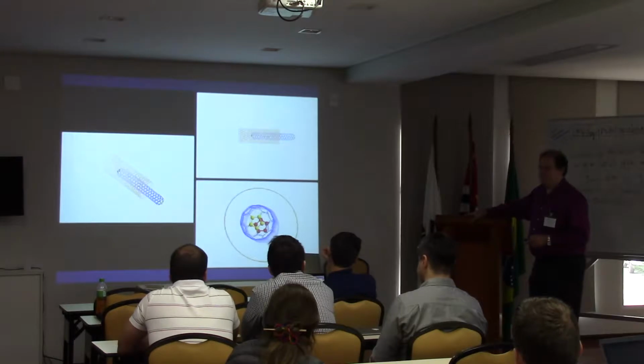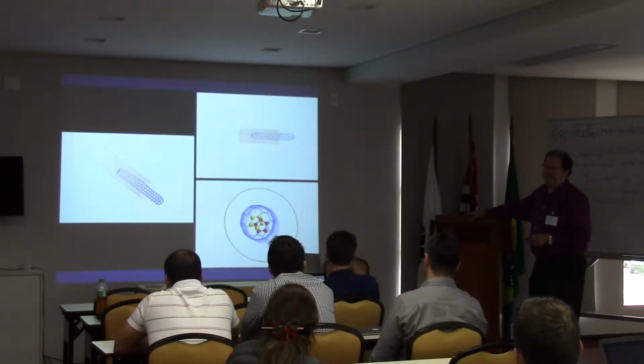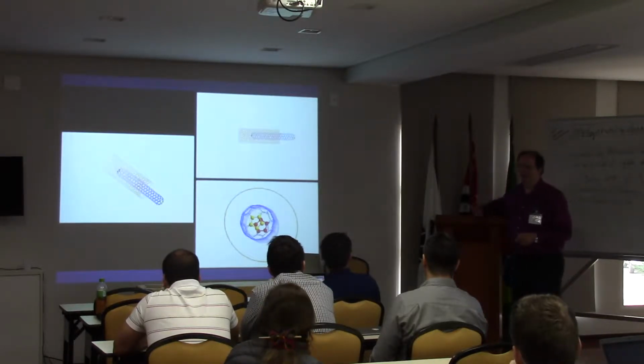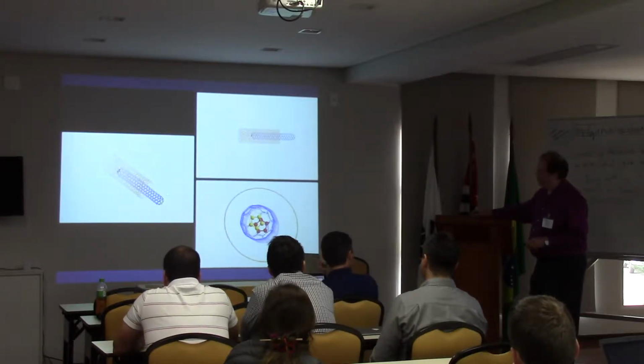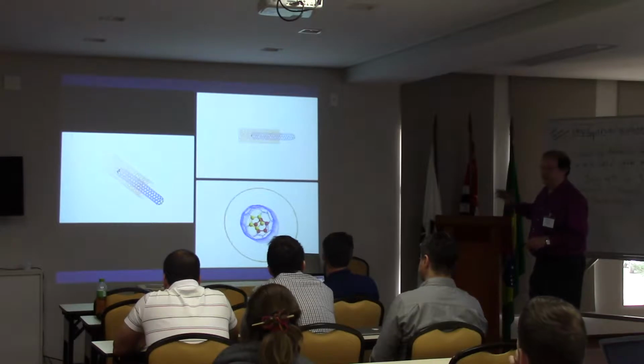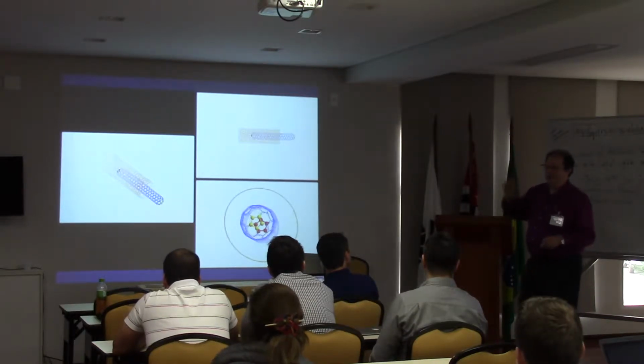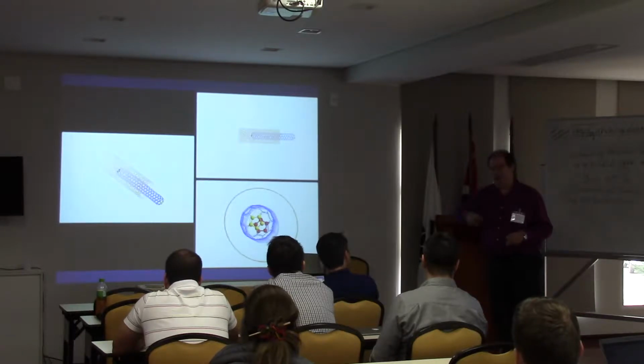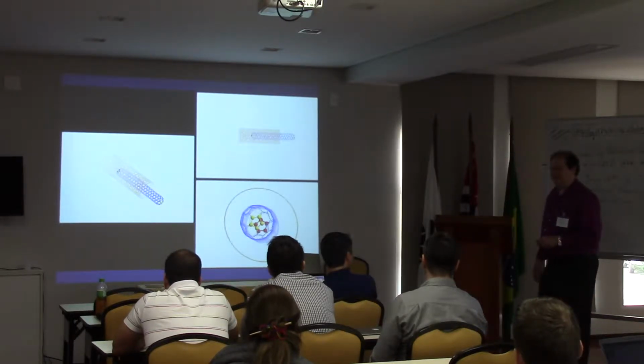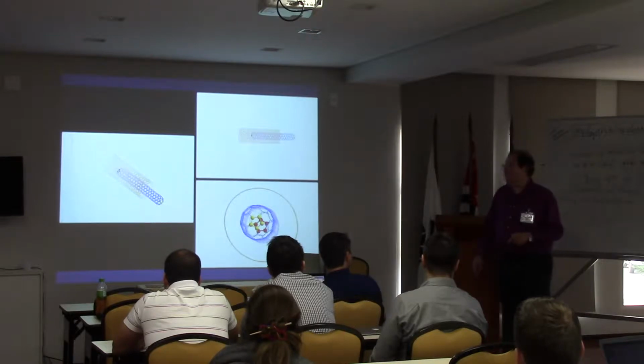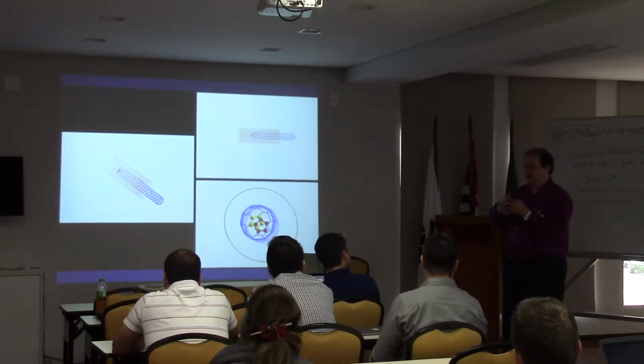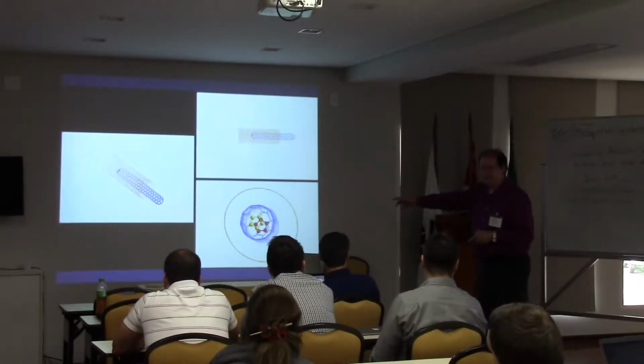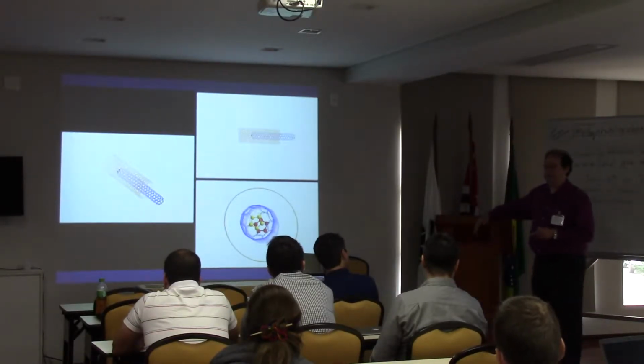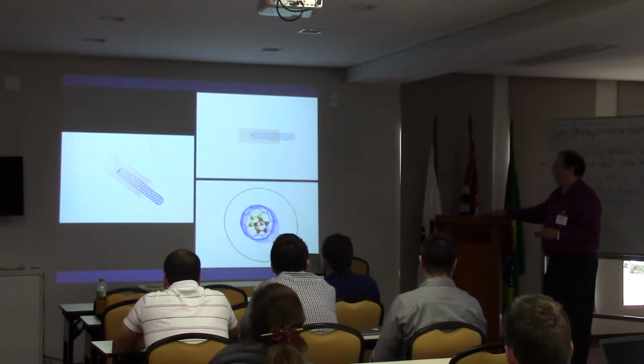So in this simulation, you have actually pulled the inner one back? No, we just gave it an initial velocity, a kick, and then it keeps going back and forth. When it's close to the end, the van der Waals interaction pulls it back. When it's inside, it's the opposite. So it's like a real pendulum. And there's no dissipation? Almost no dissipation, because it's just van der Waals interaction. If you have a perfect matching, the dissipation is very low. Almost forever, but okay.